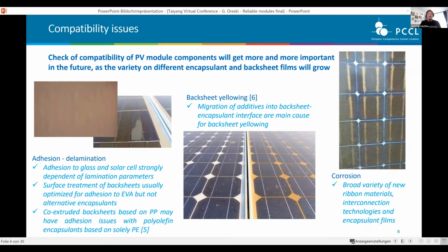Because what's the matter with adhesion? On the one hand, adhesion is strongly dependent on lamination parameters, and it's coupled, for example, with the cross-linking. But when you reduce temperature or time in order to get faster and save money, maybe you get less adhesion than needed, and on the long term you get delamination.